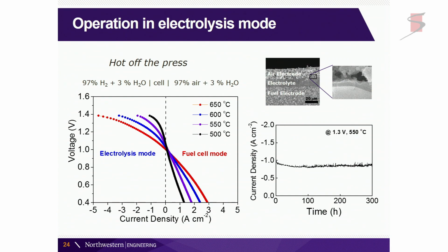And again, if we compare these numbers to what we heard perhaps earlier, these are many amps per centimeter squared at what's considered the neutral voltage, which is around 1.3 volts. We have many amps per centimeter squared as the polarization that we're getting out of this. So unfortunately, science reviewers decided this was too good to be true, despite the fact that I'm extremely careful. So if you were one of those reviewers, we are really careful. In any case, it works well, and it lasts a long time. Again, we can't use our stations for very much longer than several hundreds of hours, but we just took this out because we were tired and had to put another station in.